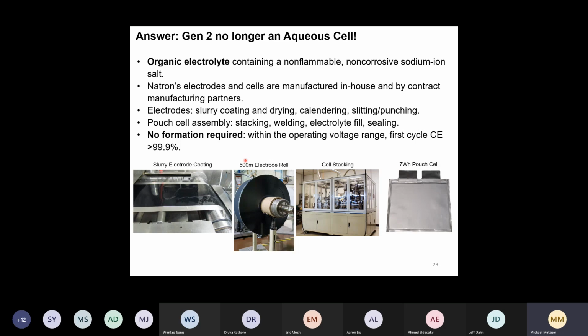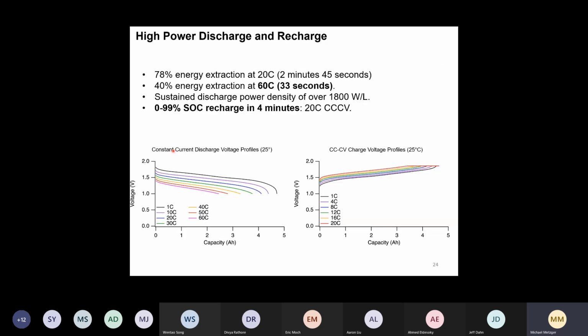And something I already mentioned, which is really neat for their technology: since it is an organic electrolyte, the electrodes operate in the stability window of the organic electrolyte. Even in the first cycle, the Coulombic efficiency is already 99.9 percent or greater. So there's no passivating reaction happening at the electrodes. No SEI formation is necessary to make these electrodes work in these voltage ranges. So that's a good thing. It saves cost and is good for electrode kinetics. And the real selling point of their battery is, first of all, it's fairly cheap.